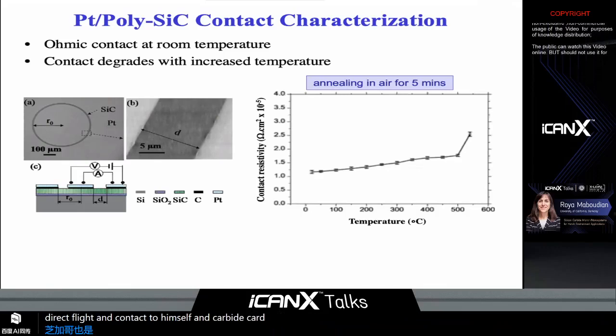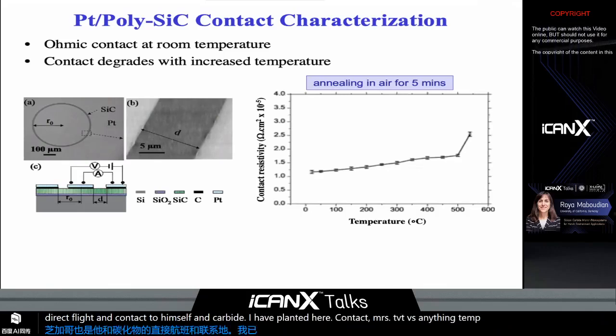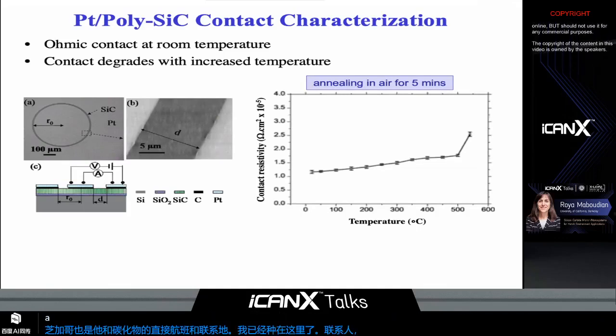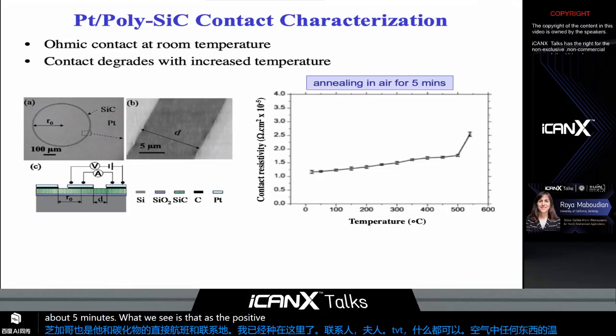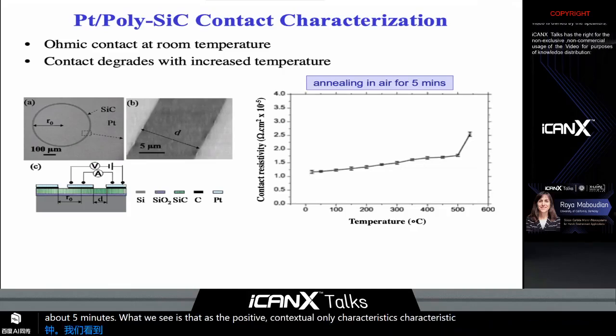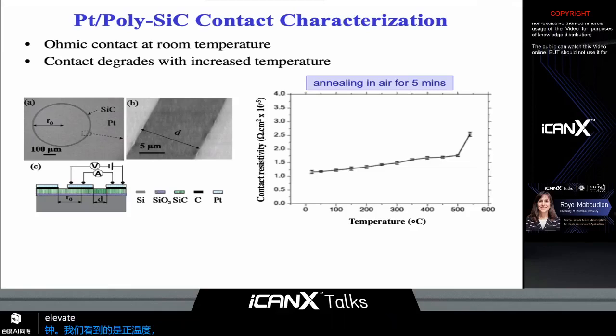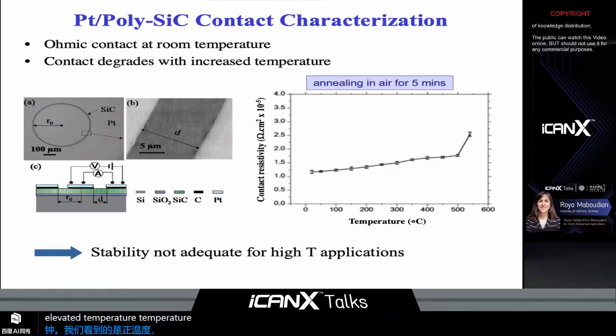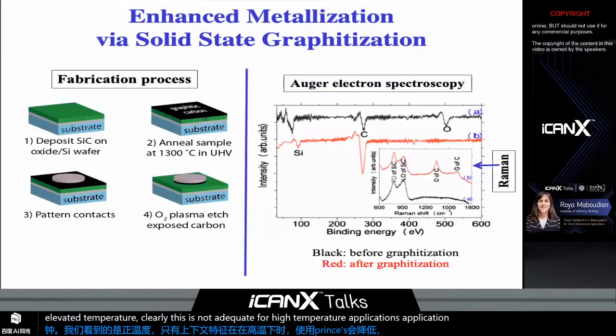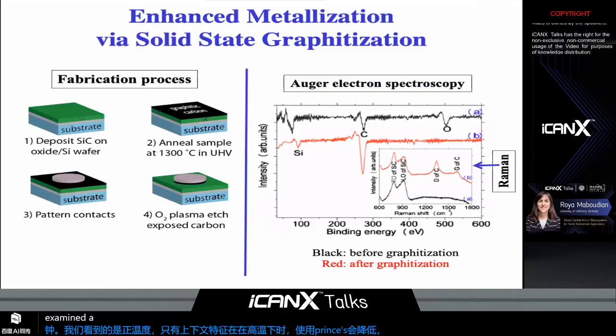I've plotted here contact resistivity versus annealing temperature for annealing in air for about 5 minutes. What we see is that the as-deposited contact shows ohmic characteristics, but it degrades, it increases readily upon exposure to elevated temperature. Clearly, this is not adequate for high temperature applications. To enhance the stability of this contact, we examined the effect of solid-state graphitization of silicon carbide.